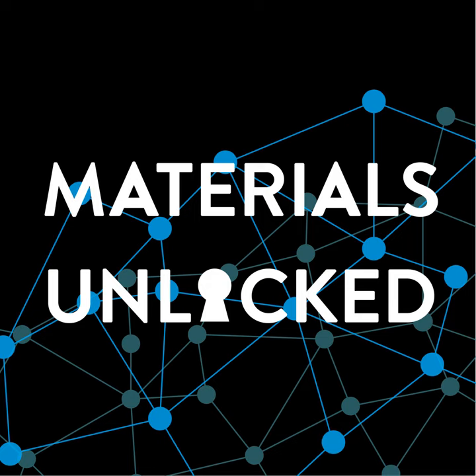Sorry, you mentioned the radioactivity and the damage. You mentioned the strength of the material, yep. And you also mentioned the creep life. Could you perhaps just explain what creep life is? It's effectively an ongoing process in materials. It's accelerated by temperature. And basically, any material that has an applied load on it will deform gradually over time. And as I say, as the temperatures rise, that deformation will increase. So it's effectively like hanging a weight off of some blue tack is the analogy I use. Gradually that blue tack will start to stretch. And the same thing happens in materials.